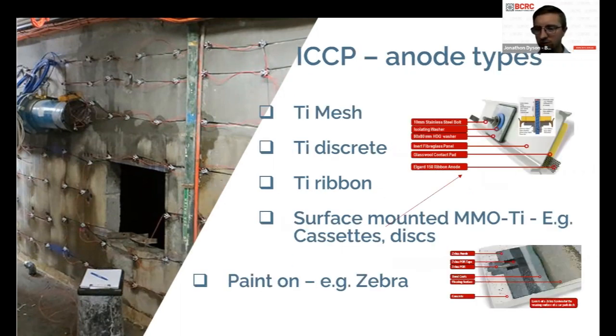Impressed current anode systems include things like titanium mesh, titanium discrete systems, which again are drilled into the structure. So a mesh system is one which is probably good for when you're covering a large area like a wall or a slab, and a titanium ribbon structure which can be embedded into slots. There's also things like surface mounted mixed metal oxide titanium anodes, which can be mounted to the surface, and they come in things like cassettes or in discs.